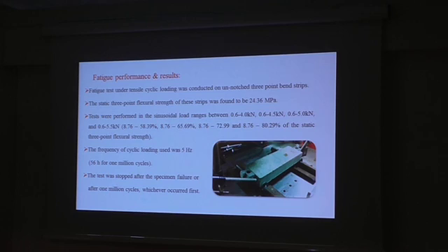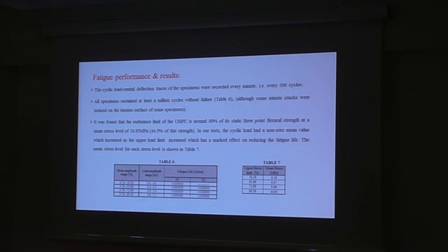The frequency of the cycles used is 5 Hz, which is about 56 hours to complete 1 million cycles. The test was stopped after specimen failure or after 1 million cycles, whichever occurred first. The cyclic load-central deflection of the specimen was recorded every 1 minute, that is, every 300 cycles.